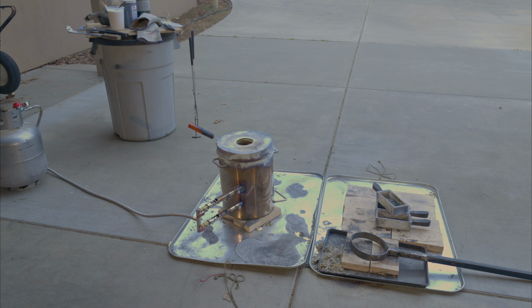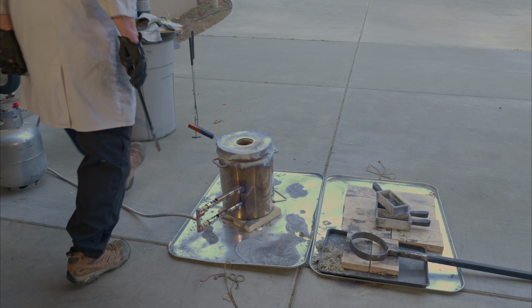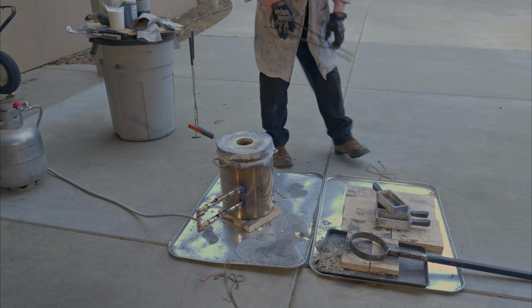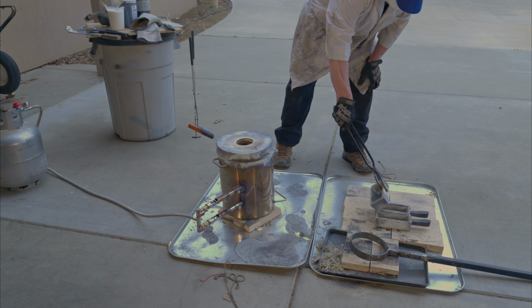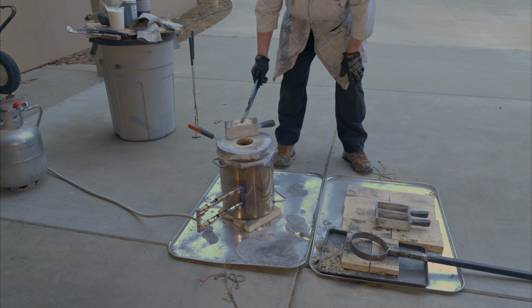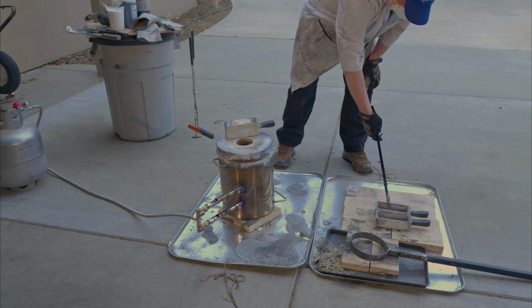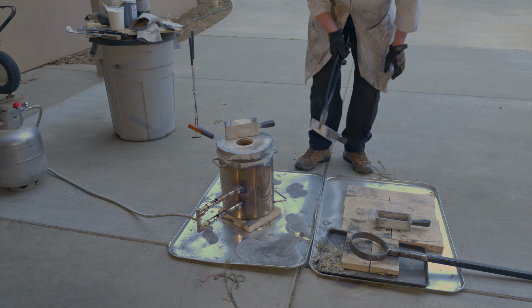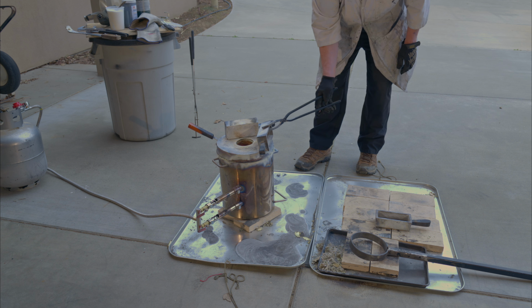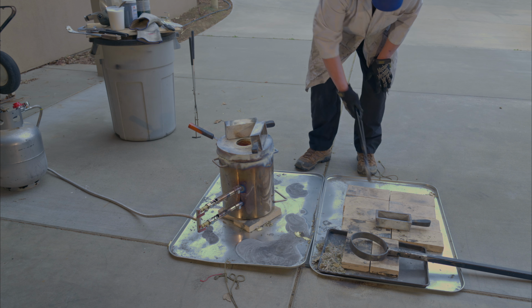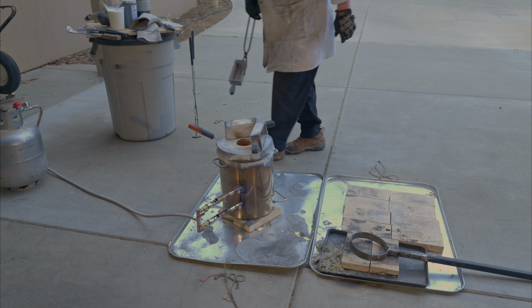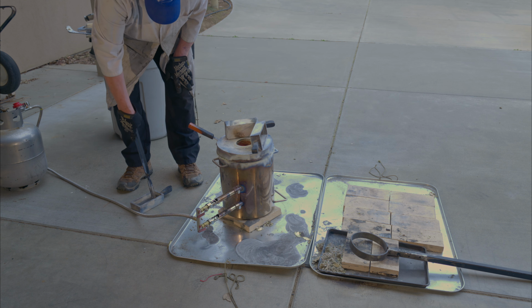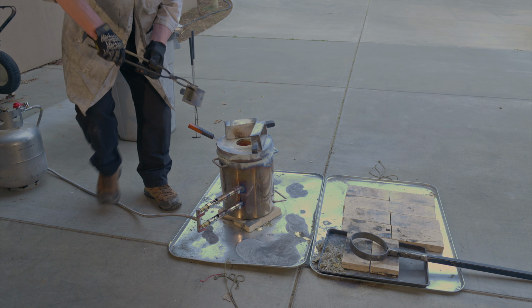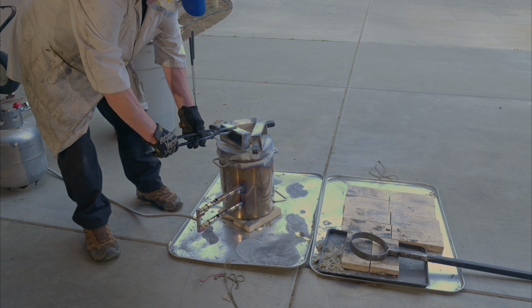It's time to prepare the molds for the pour. We want them to be dry and moderately hot so they don't chill the brass too fast when it's poured into it. I just take them and lay them up near the exhaust port of the furnace and heat them up to approximately 450 degrees Fahrenheit. And that takes place in only a couple minutes. Once they're hot, take them, lay them back on the refractory brick, and get ready for the pour.